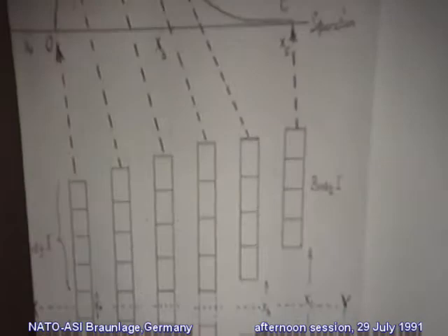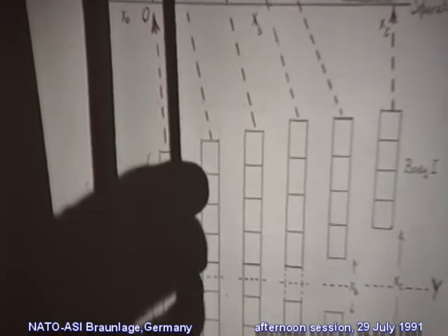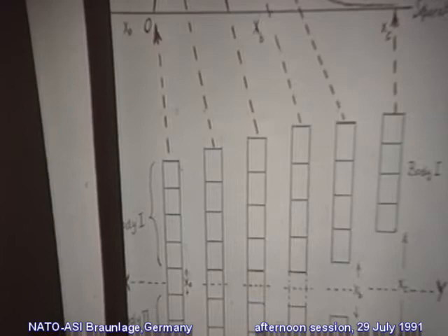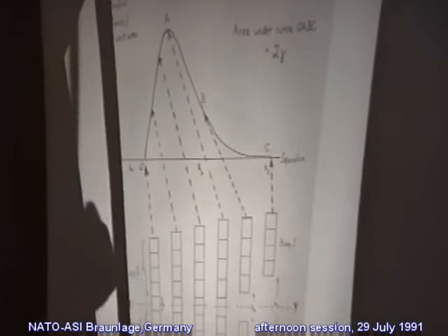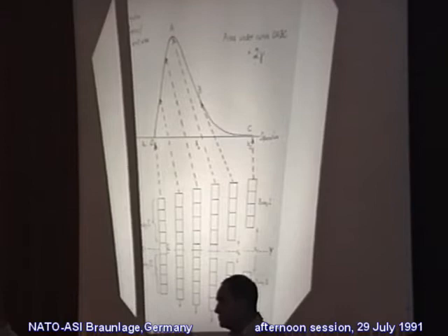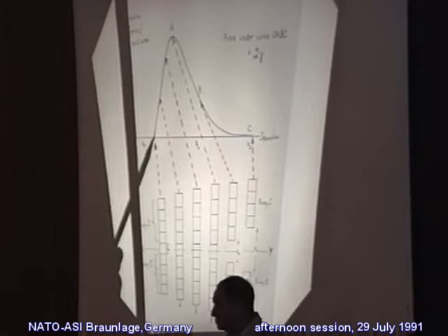Can you imagine trying to do the particular experiment which is depicted here? You have two ways in principle of doing it. You can impose a displacement and attempt to measure the force, or impose a force and measure displacement. Invariably, you would be relying on a spring stiffness to sense a force through a displacement. So this point will come up, I'm sure Professor Maugis will speak about it in terms of viscoelastic peeling later, and instabilities. Mike Adams mentioned it. So you can obtain stability in a conventional experiment in this region.